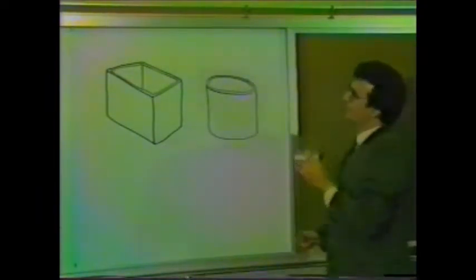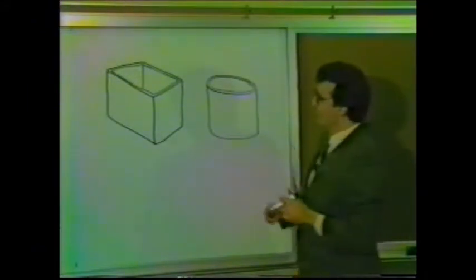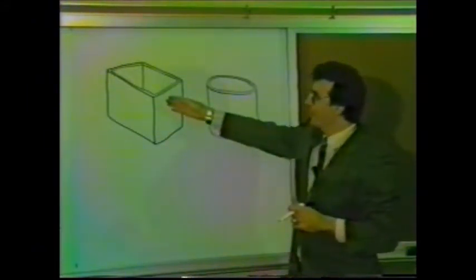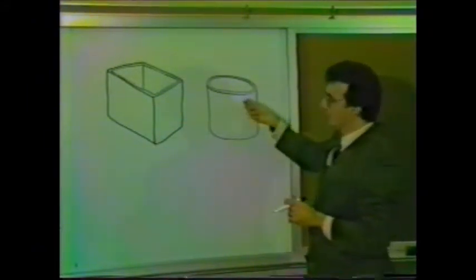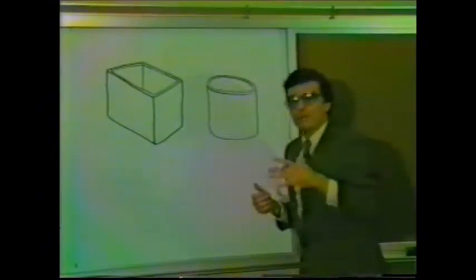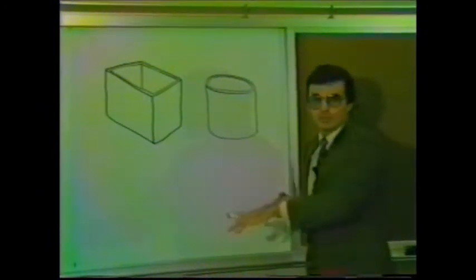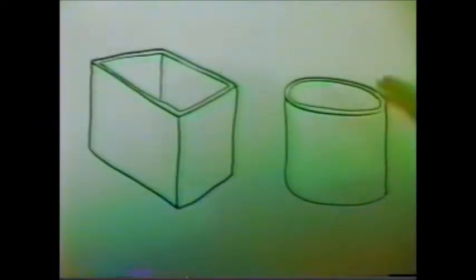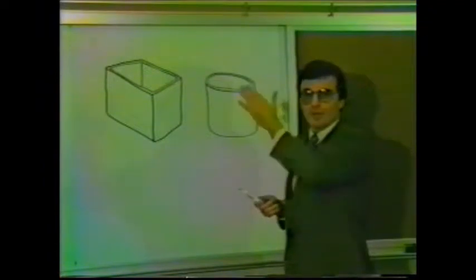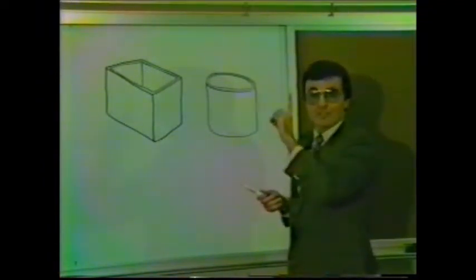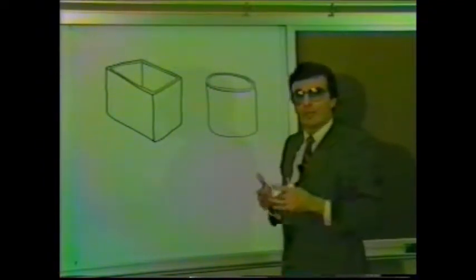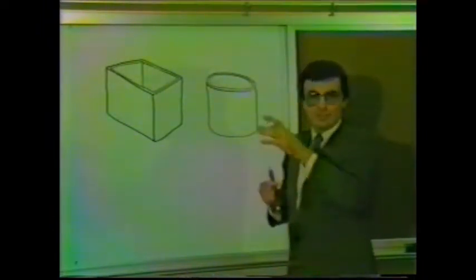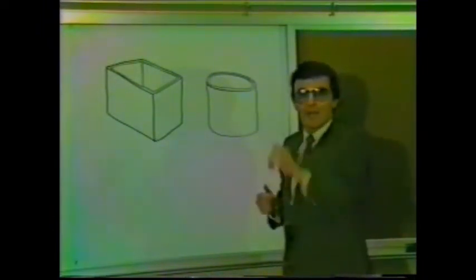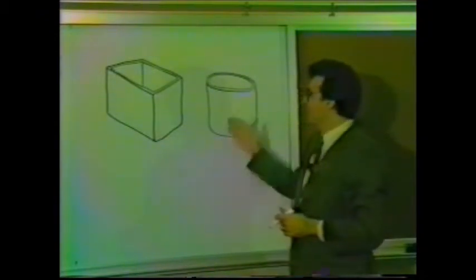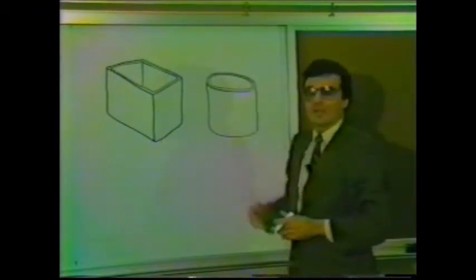And besides the uniformity, the strand casting process, be it with the square or rectangular versus rotational circular molds, allows you to improve the yield of the steel, because as you're pouring all of the steel through, all you have to do is discard the very end of the cast one time. Again, comparing that with ingot steel, for each ingot you would have to throw off the very tops of the product. So there is a yield saving with strand cast steel.